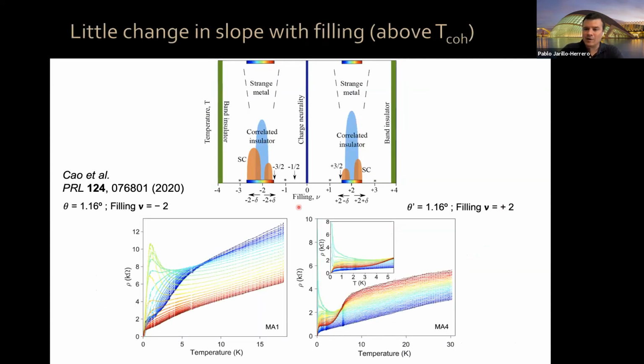You can study this in the system again. One of the advantages of magic angle graphene compared to many other correlated systems is that we have continuous electronic control over the doping in our system. So if you look at the resistivity versus temperature at each of these dopings, where the colors correspond to the color scale here, you can see that the linearity is best around the correlated insulator state, but it's also pretty much linear all the way around the range that encompasses both domes, of course once you get out of the superconducting state.